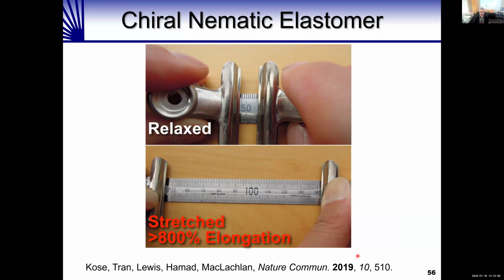As I mentioned, this is an elastomer. So when it's relaxed, you can see it's colorless and transparent. And when you stretch it, it remains colorless and transparent, but we can stretch it up to 8 times its original length, and it's completely reversible. This is a beautiful elastomeric material. Unfortunately, for the longest time, we could not get structural color.